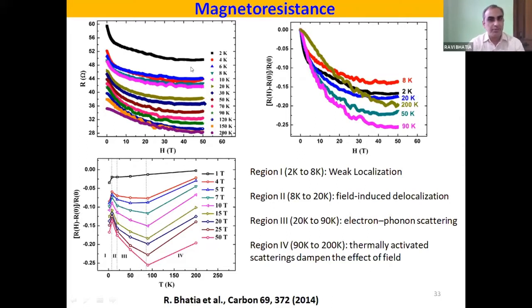But the important feature here is, when we converted this graph into the magnetoresistance, there is an entanglement between the temperature and the magnetic field. What is the meaning of entanglement? In general, at the lowest temperature, the magnetoresistance should be maximum, because all the phonons are frozen out. So at the highest temperature, it should be the least magnetoresistance. So this particular graph does not present anything.